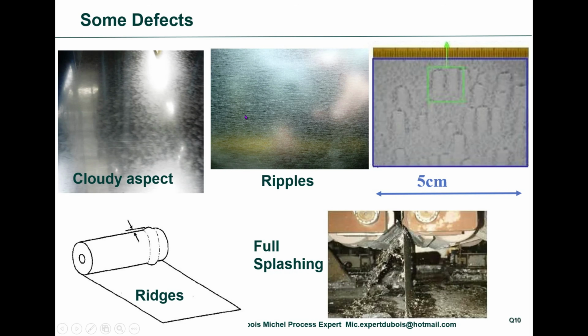We have the question of ripples. There are different types. This is typical ripples on thin sheets. It's related to the fact that the gas flow is not stable. It vibrates this way, and because of that it makes those types of ripple and waviness. This one is typical of low speed. You see this comet shape. I think it is related to oxides that are formed and that impact the backflow going back to the strip.